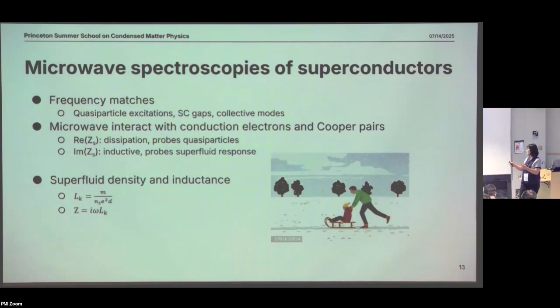So 1/2 Li squared, that's the energy this circuit has in the inductor, is exactly the energy, or the kinetic energy, of all those Cooper pairs. Then you can calculate the inductance from that equation, and you directly get that the inductance is 1 over the density of Cooper pairs, or superfluid density. And then the impedance is just i omega times this inductance. So that's how the intrinsic property of the superconductor is related to a quantity that microwave spectroscopy can measure.